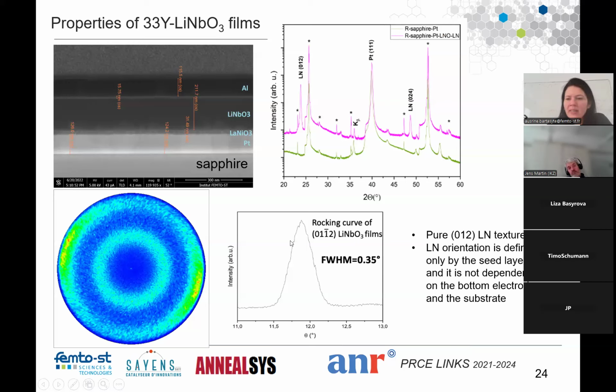But again, we use the platinum, which is sputtered, which is 111, and again, sputtering of lanthanum nickelate, and then we grew lithium niobate. So we had a very nice rocking curve, and we had some preferred orientation. I don't show it, but basically, even though we grew very fast on platinum and sapphire, in 2 minutes we grew 100 nanometers.